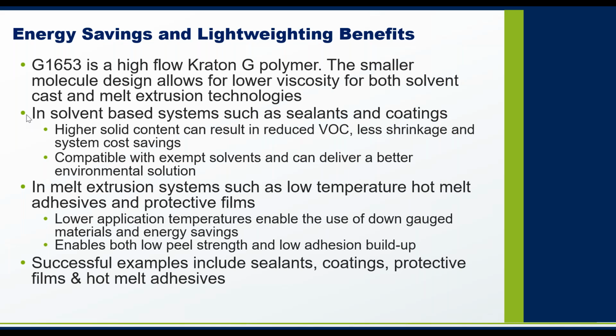And then a lot of our polymers are compatible with exempt solvent systems, and that can deliver even better environmental solutions. In the melt, lower application temperatures help enable the use of down gauge materials and energy savings as well. And these polymers also enable both low peel strength and low adhesion buildup, as well as great UV resistance because these are fully hydrogenated grades.